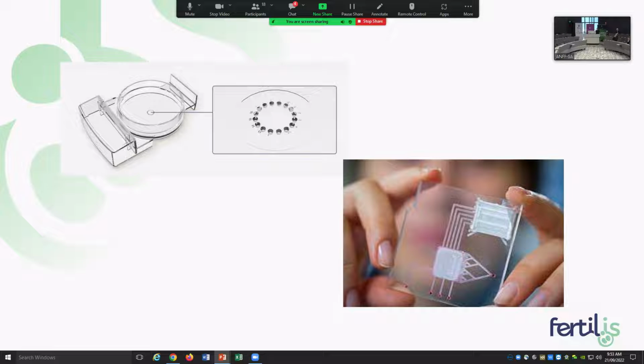Not so for IVF. For IVF, it's a sample that matters. We want the embryo at the end. PDMS doesn't really lend itself to that. It doesn't have the precision in terms of the geometry to allow us to collect the sample at the end and collect it successfully. The other issue with PDMS as it relates to IVF is that it's water permeable. So it will start to absorb water from the media. For IVF, what this does is it changes the osmolality of the media.